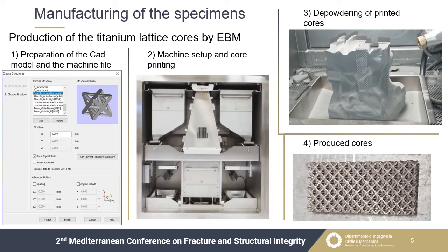Then, the machine was prepared for the manufacturing run. The powder reservoirs were filled, and the process parameters were set. After, the vacuum was drawn in the manufacturing chamber. The electron beam was calibrated and the manufacturing chamber was preheated at 700 Celsius. As the imposed temperature was reached, the specimens were built according to the typical sequence of a powder bed additive manufacturing process. At the end of the process, the chamber was cooled down and the specimens were extracted from the unmelted powder and cleaned in a suitable chamber using pressurized air and a sandblasting machine, while the final depowdering operation was carried out in an ultrasound bath.